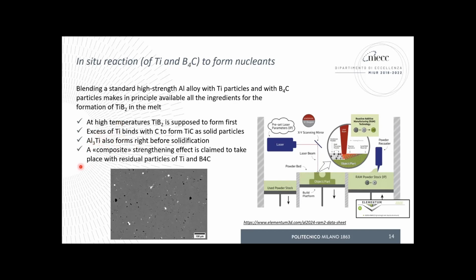And also they claim that there is a kind of composite effect, because the residual particles that remain in the structure, the titanium, the white ones, and then the boron carbide particles, the black ones, remain in the matrix to generate a kind of composite material. I'm not aware how much the strengthening will be with that very small percentage of particles, but in any case, we won't deal with that in my talk today.